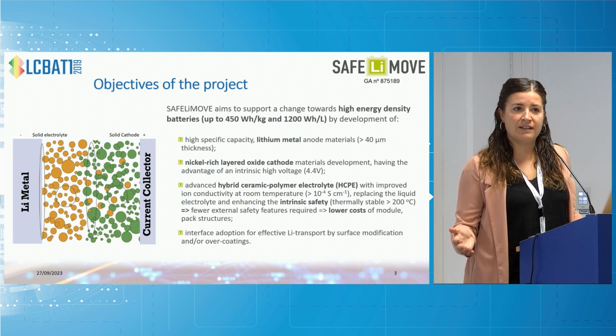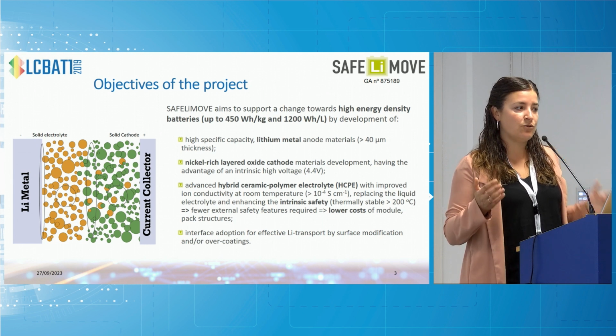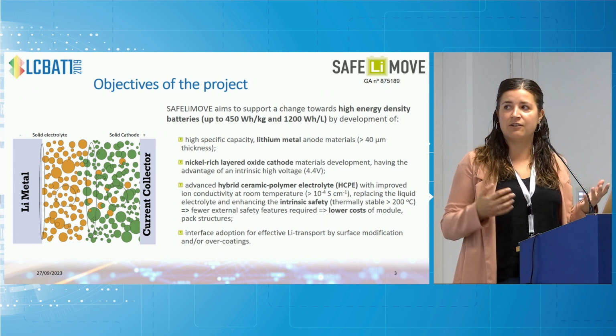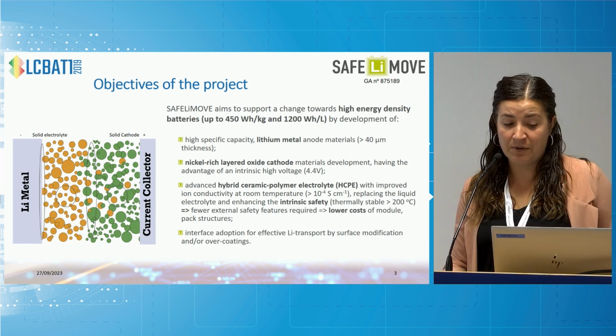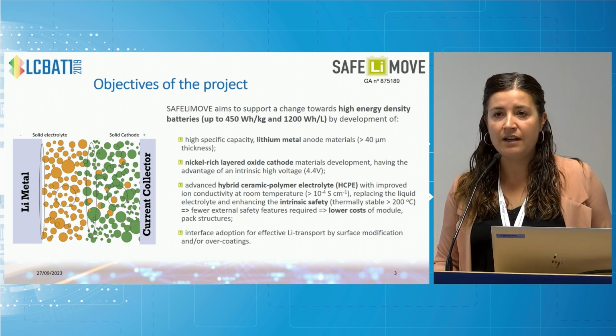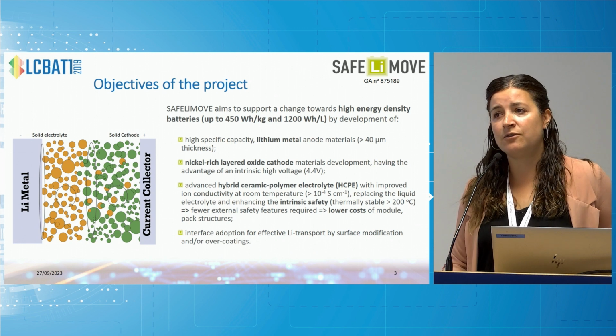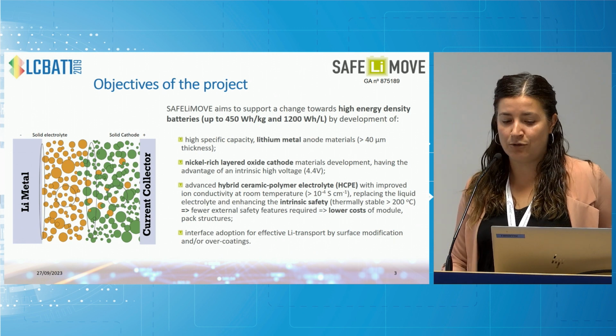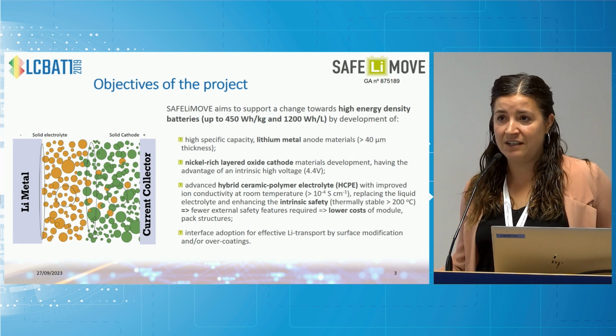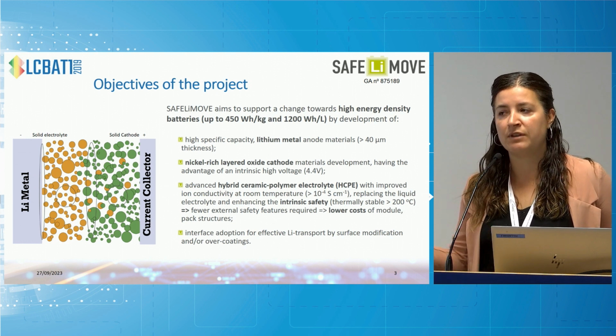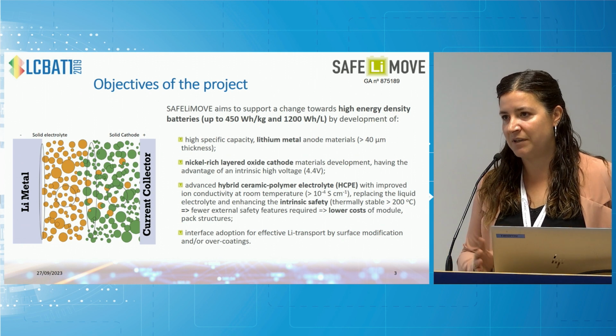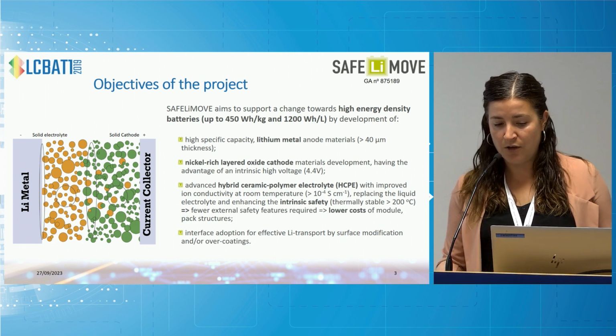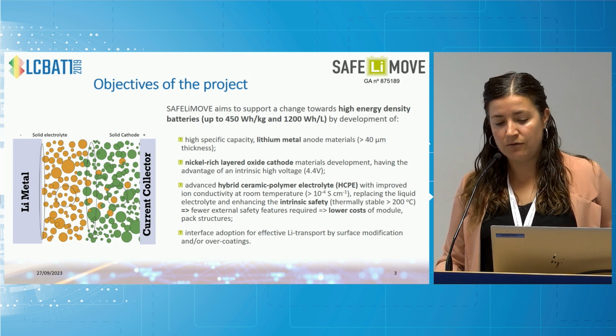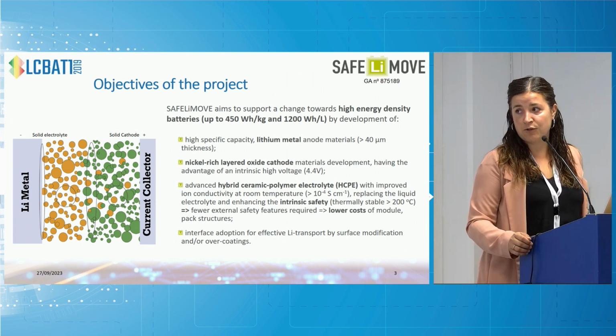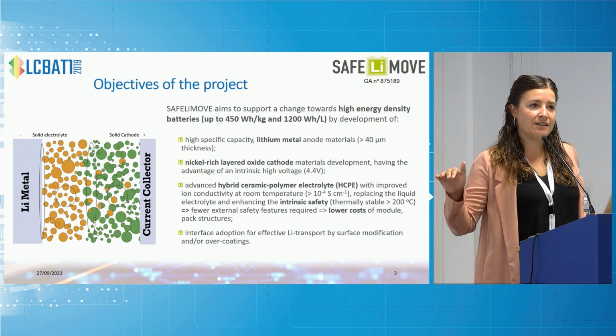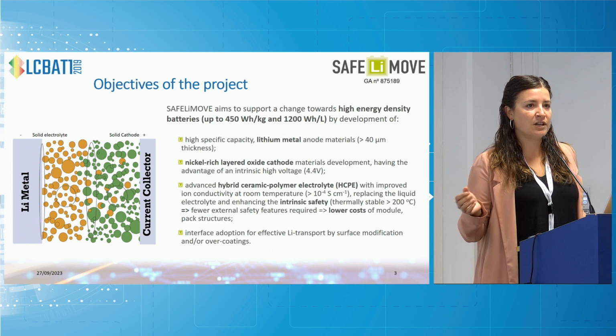And then we have the electrolyte. In this case, our strategy was to combine the best of both phases, inorganic and organic. So for that reason, we decided to work with a hybrid ceramic polymer electrolyte, HCPE, aiming for high ionic conductivity beyond 10^-4 Siemens per centimeter at room temperature, as well as high thermal stability to provide the safety of the battery, even if we know that the electrolyte is not the only part of the battery that we need to work on to guarantee the safety, and also looking for decreasing the battery cost.